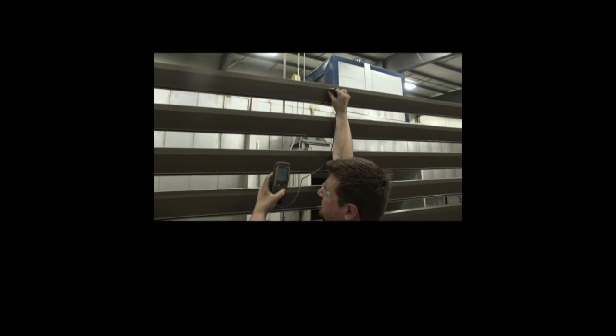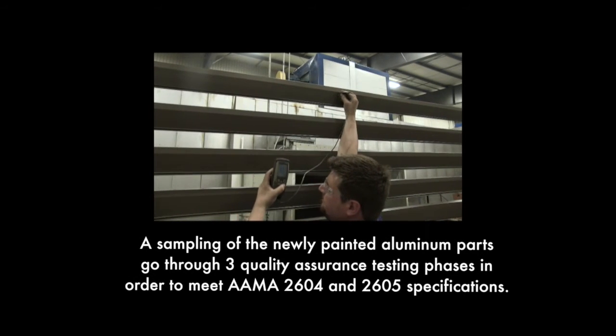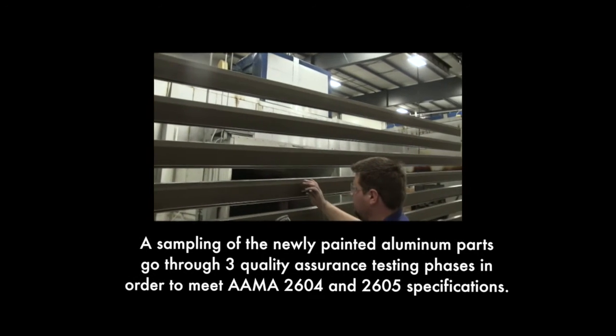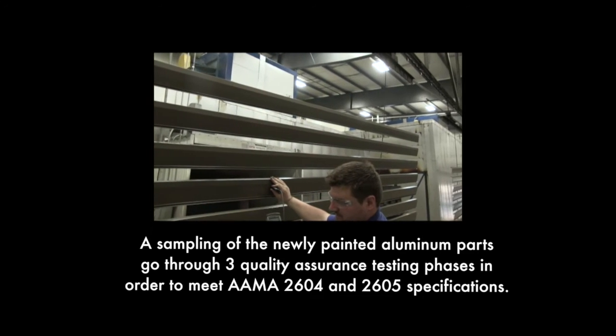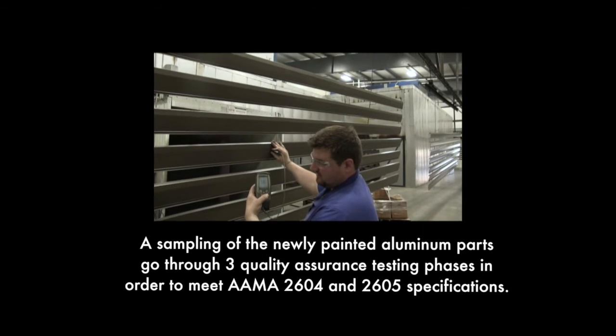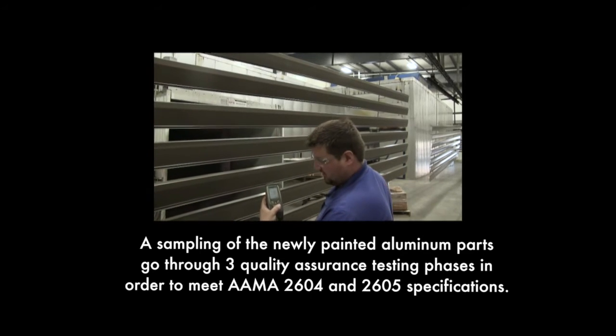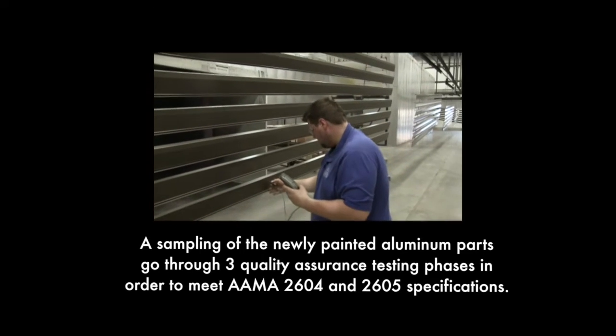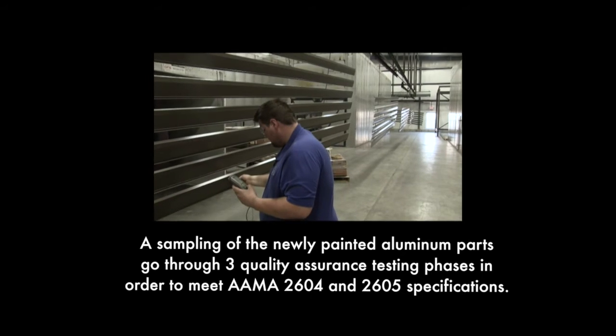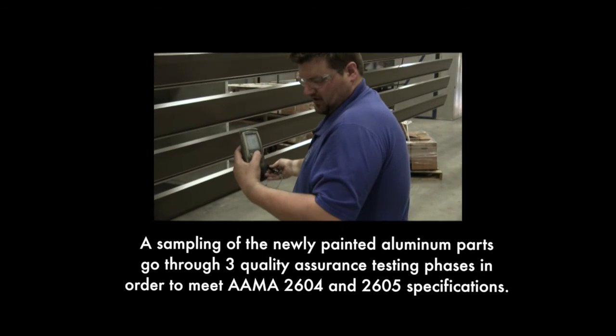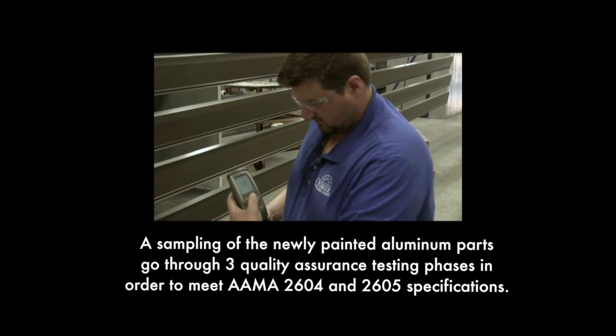Once fully cured and before it's released to manufacturing, a sampling of the newly painted aluminum parts go through 3 quality assurance testing phases in order to meet AAMA 2604 and 2605 specifications. First, the mil thickness will be measured on each batch of the painted material. This guarantees a consistent and even coating of paint. Once the mil thickness is verified, a sample of the painted material is removed by quality control for additional testing before the product is actually released to manufacturing.